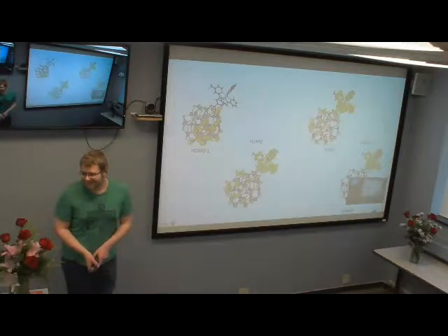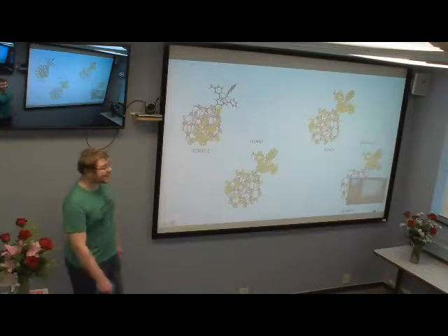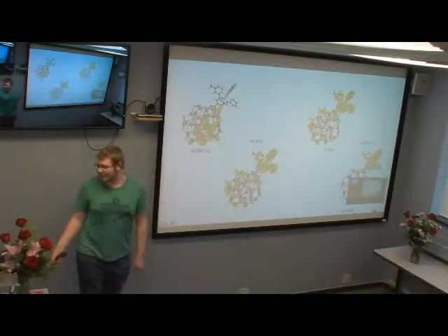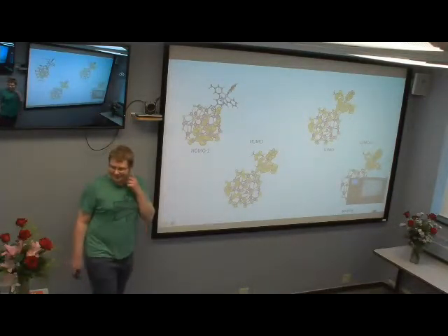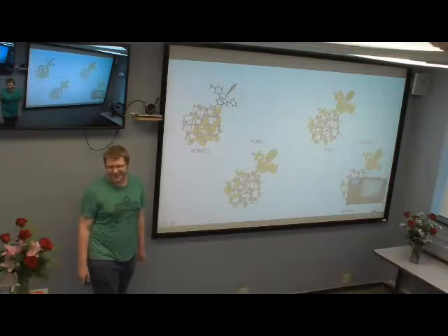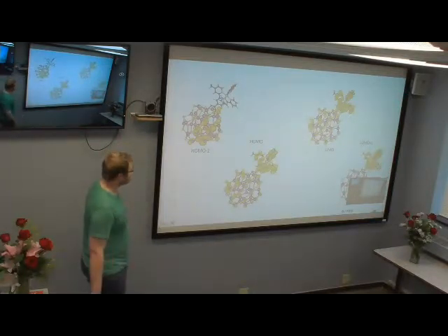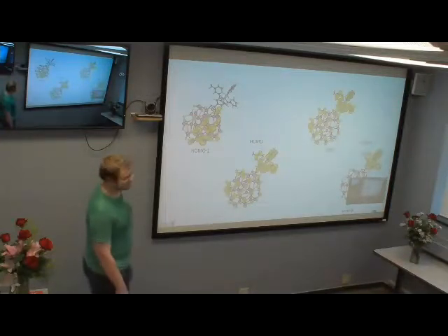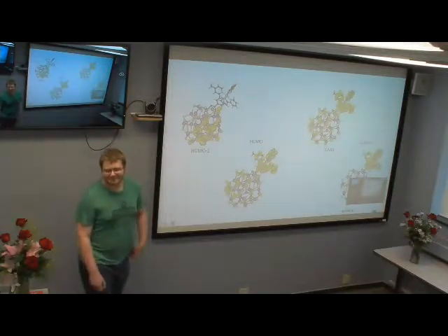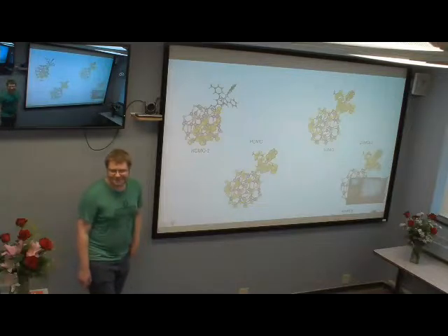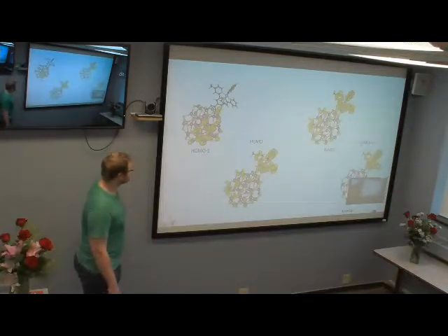You already charge your system. I mean, you put 0 charge, but what should be the right charge on this system? The right charge should be +1. So it means you already add an additional electron. Yes. You can think that you already have it, let's say, between the LUMOs, right? Put some voltage, and you already populate the state which should be unoccupied, right? You populate with an additional electron, making the system neutral, but in reality you're really adding the electron there, right? And this probably results in this kind of charge transfer character.